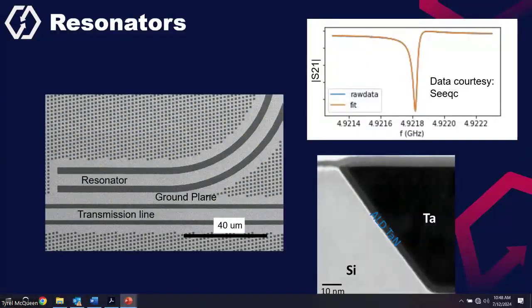It serves two purposes. So one purpose is, in order to do the chemical mechanical planarization, the pattern density across the wafer should be uniform. And for that, first let me describe the pattern. So this is a transmission line. Across this, a microwave signal is going, and then there is a coplanar waveguide resonator here, and we are measuring this transmission S21 as a function of frequency, and the dip is basically the resonance frequency. And then we have a resonator here. Then there is a ground plane, which is basically the metal around it, and this is silicon.